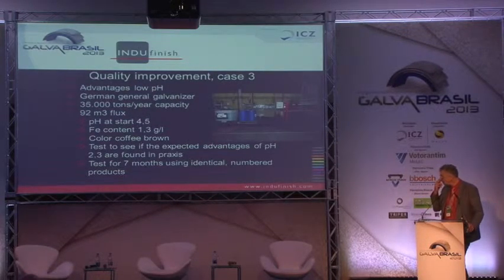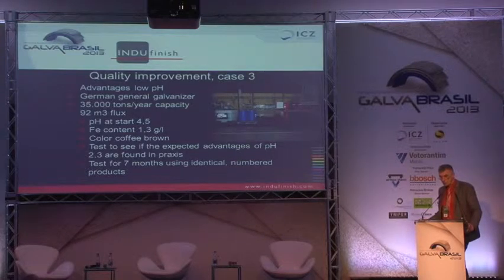Case 3. They were already operating at 1.3 grams a liter, so we didn't worry about that. They were operating at 4.5. We brought it back to 2.3, and we set up a test program of 7 months. That meant we bought a pallet of tubes, and we did a galvanizing test every month. At the same time, we cleaned the galvanizing filter first, so we had exactly the same circumstances.